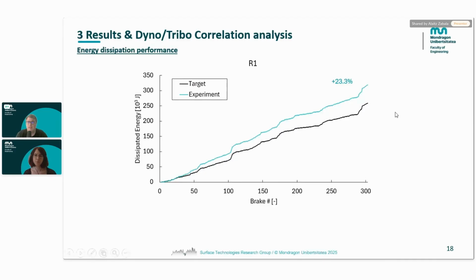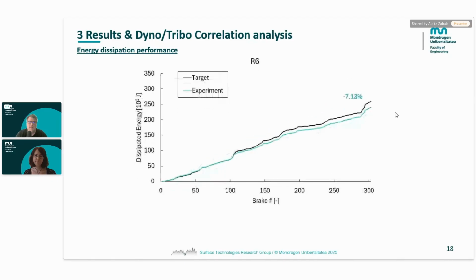For the first repetition, we have like 23% more dissipated energy. This is quite high, but once the algorithm that corrects the friction coefficient kicks in, we can compare the performance on the last repetition, and the result that we obtain is quite good, around 7% difference. Usually in tribological tests, differences around 10% are quite normal, so this lies within that value.